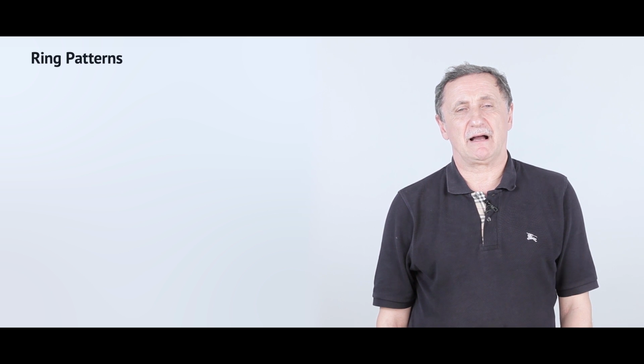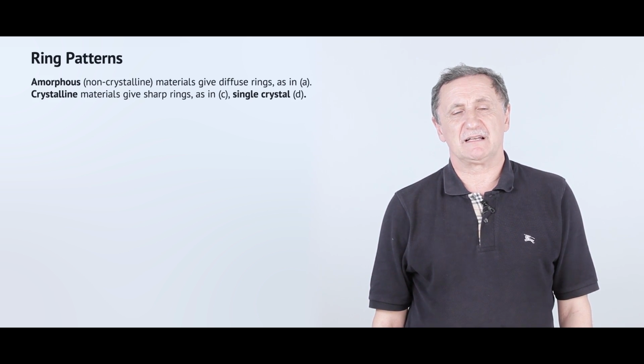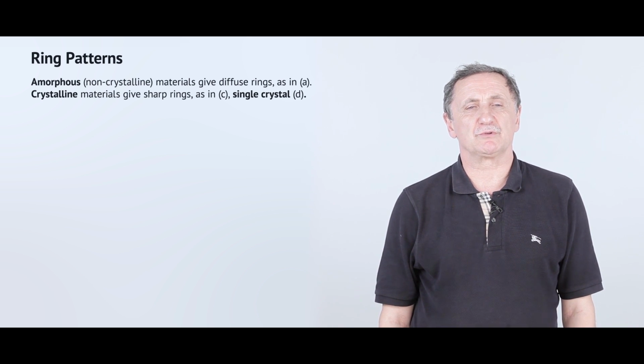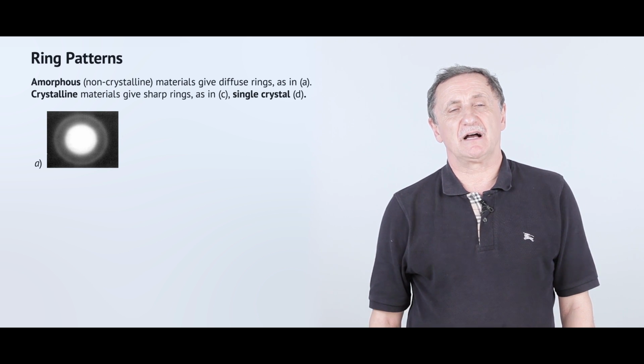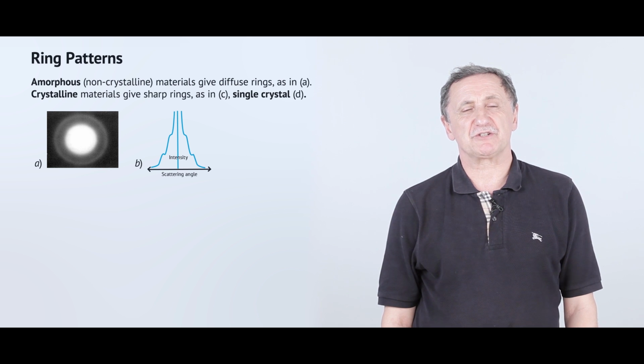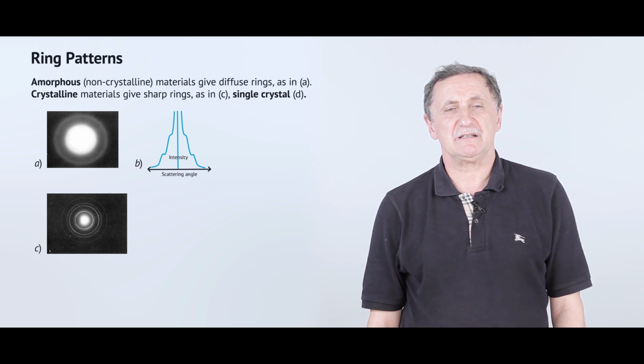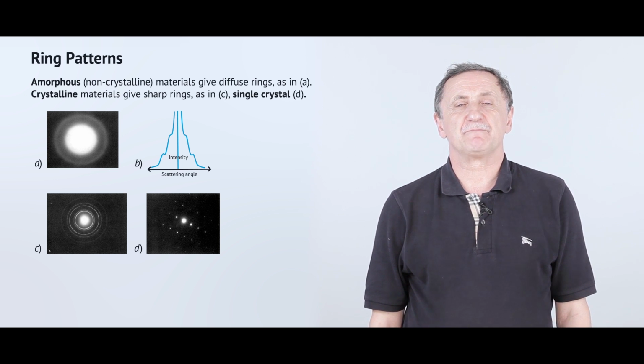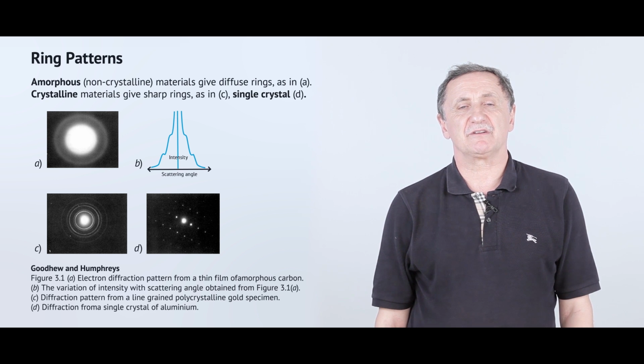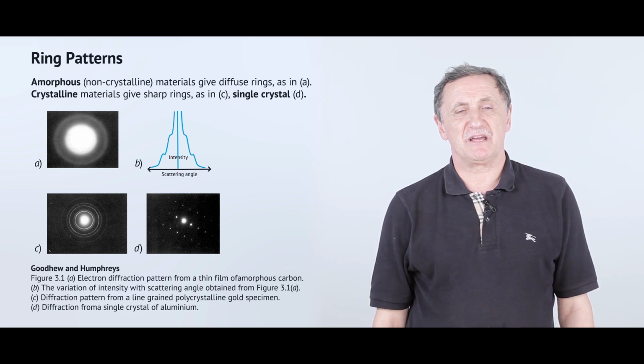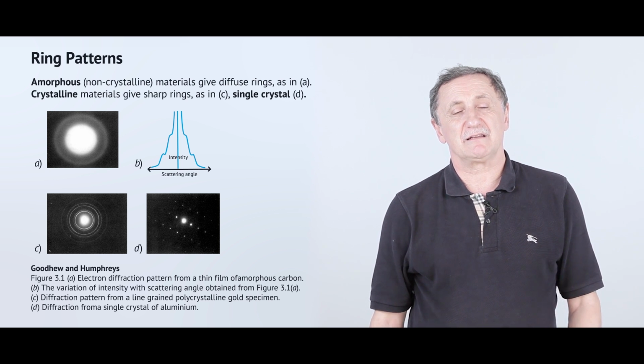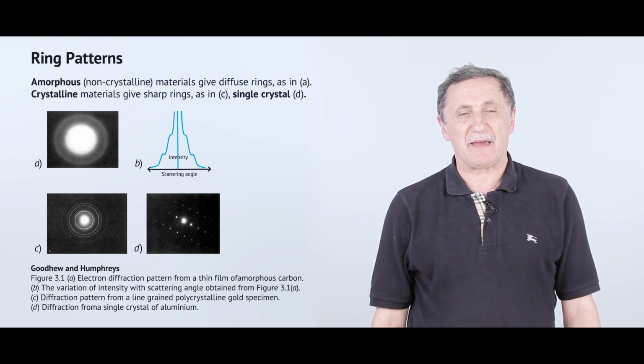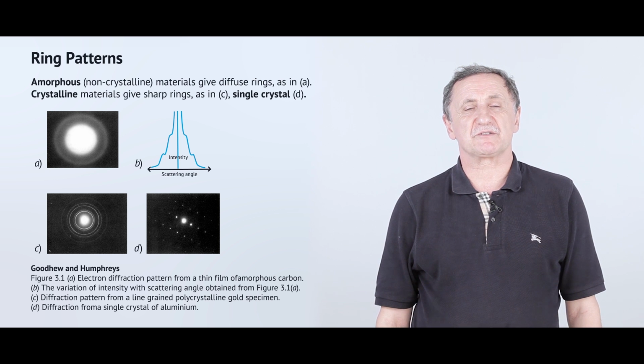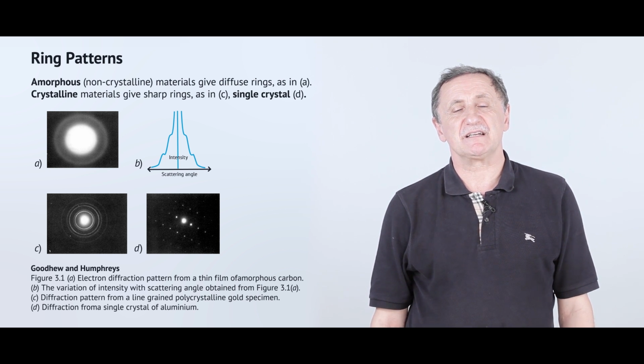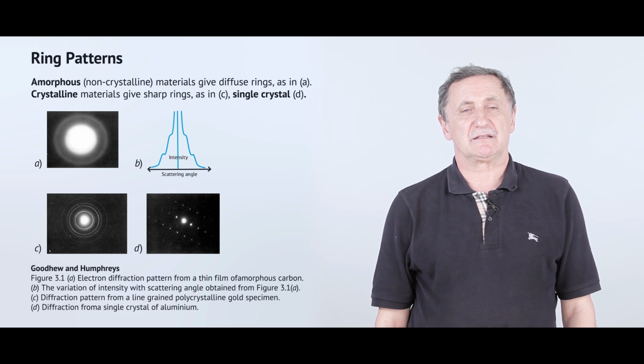So again, what information can be obtained with the help of electron diffraction? First of all, you can conclude whether you have amorphous material. This image of diffraction, that is a fuzzy picture of diffraction, you can see in the upper left corner of the screen. Then you may conclude that maybe it's crystalline material, polycrystalline material. In this case, you will see rings, and you can measure the diameter of these rings, and based on this information, you can then obtain the data on the d-spacing of this crystal structure, or you may see several spots which will indicate that you have a monocrystal, a single crystal in your view, and again you can obtain information about the parameters of this single crystal.